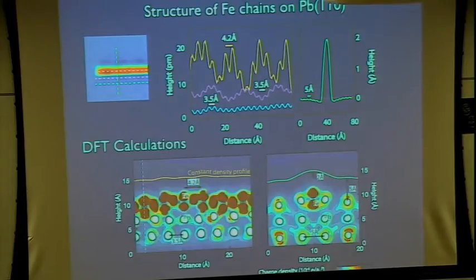So question. These are actually very detailed information, and if you want to think about it, this is determined by the band structure of the lead system you have and the iron. These are things that you should be able to calculate if you know the structure of what you have made. DFT calculation is very good at capturing these details of STM images. And this is where we started working with Alan and his postdoc Ha to figure out what we have built.